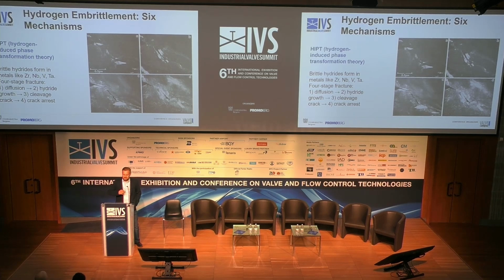Okay, so the metallic structure, the shiny, very strong, very resistant structure is not there anymore. You're getting something similar to sand, clay, let's say. And this characteristic is actually what makes the crack. After you lose the structure, you lose the resistivity, the crack starts, and once it started, it stops at some point. That's the diffusion of the mechanism. So you have the interaction, formation of a new molecule, the crack formation, and once it's done, you're done. There's no turning back from that point.